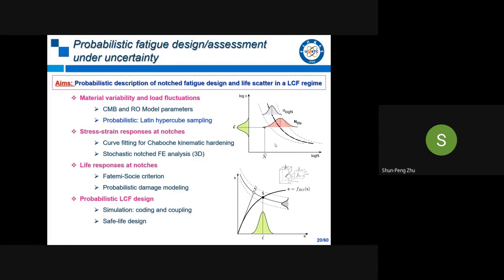And for the mentioned uncertainty, for this first case, we try to locate the material reliability and the load fluctuation, based on the Coffin-Manson-Basquin equation and the Ramberg-Osgood model parameters, and also using Latin hypercube sampling, which is a more efficient sampling technique than Monte Carlo sampling, as mentioned by Abilio in the earlier presentation. Then we quantify the stress-strain response at the notch areas, with the kinematic hardening model parameters and also the stochastic finite element analysis.